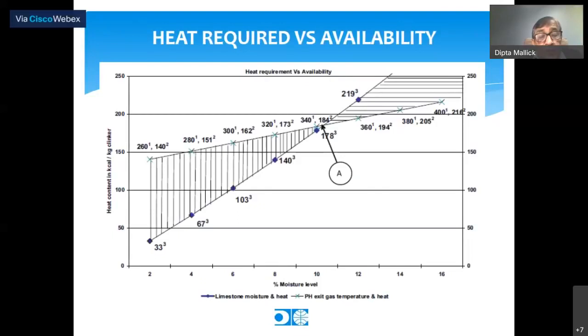And the more the moisture, naturally the more the amount of heat required in the raw meal, so the availability of heat for useful purpose becomes lower and lower. At about 10% moisture, possibly whatever heat is available in the preheater is completely taken care of by the raw mill. So you don't have anything in excess which can be utilized. And if the moisture content is more, in fact, you have to supply more heat from some other sources. So that is the situation.